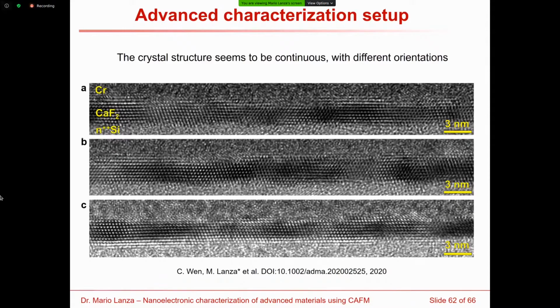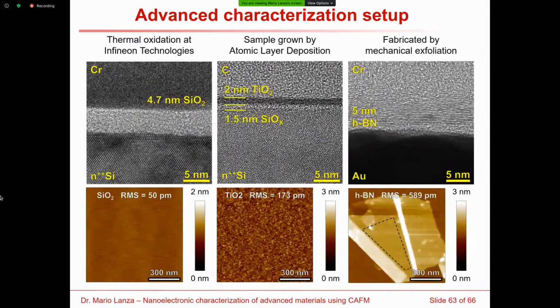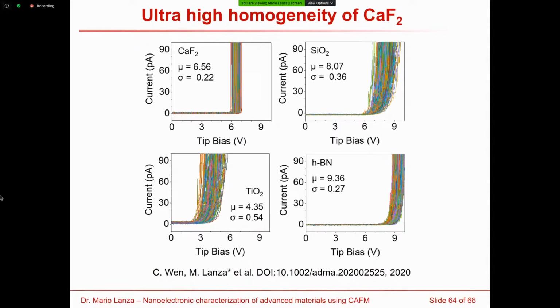And the material that we studied in this slide is calcium difluoride. Here you can see cross-sectional TEM images where you can see the bonding, and we compare this material with three other samples. One is silicon dioxide grown by thermal oxidation at the laboratories of Infineon Technologies, which means this is outstanding quality silicon oxide. Also one sample that is titanium oxide grown by atomic layer deposition, and also one sample that is mechanically exfoliated boron nitride.